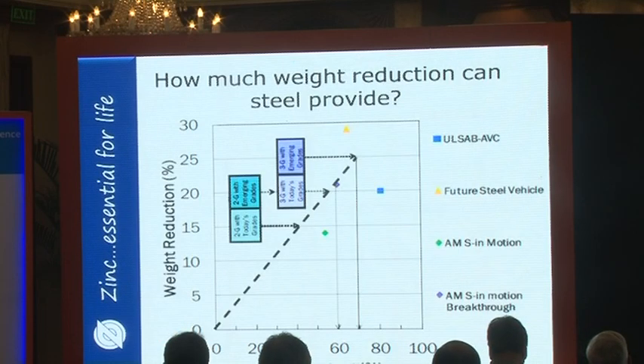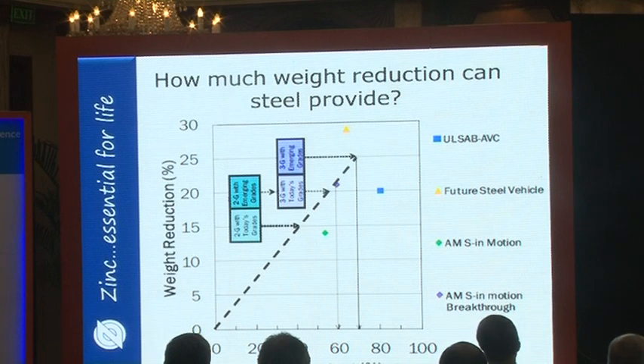So how much weight reduction can steel provide? We show here the advanced high-strength steel content marching up the curve. We are today looking at second-generation steels. We have reached about a 15 to 20% vehicle reduction these days. As we are moving into the third-generation steels, which is the grade that we are now working on developing coatability processing for, we will see this march up to 25% as we go up to 70% advanced high-strength steel content.